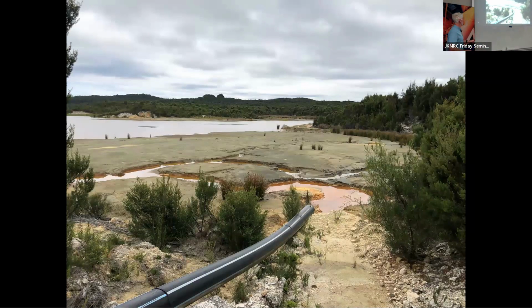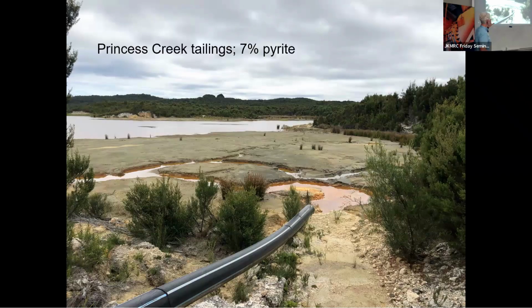Another example from Princess Creek, we're doing with Anita, that from an acid mine drainage perspective, the tailings has 7% pyrite. So it's like lots of acid generation. We've got a real problem here. The pyrite also, though, contains cobalt. It's like, oh great, we've got an acid source, we've got cobalt, let's do a biooxidation. And we did it, and the cobalt that was in solution over the next month went from, trying to remember what it was, like 20 or 30 ppm to 0. Sulfur increased, acid increased, bioleaching was happening, pyrite was degrading, and the cobalt precipitated.